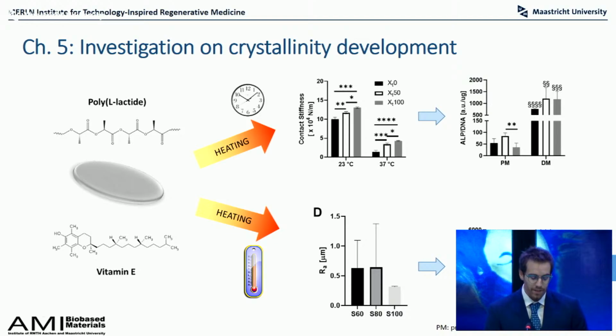From cell studies on top of these films, we noticed that cells cultured in osteogenic conditions were more responsive to films that were annealed at the highest temperature and that exhibited the narrowest standard deviation distribution and therefore the narrowest crystal size distribution. And this was particularly interesting, meaning that there is actually a range of roughness that our cells were sensitive to, but they were more sensitive not to the average roughness, but actually to the distribution of the roughness itself.